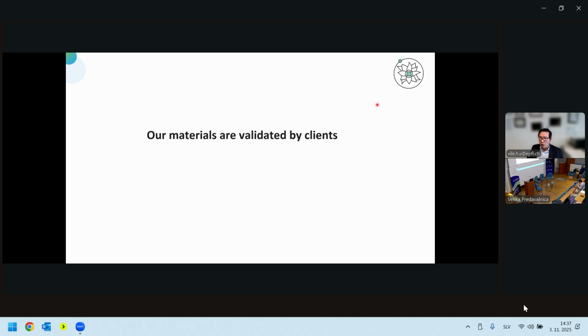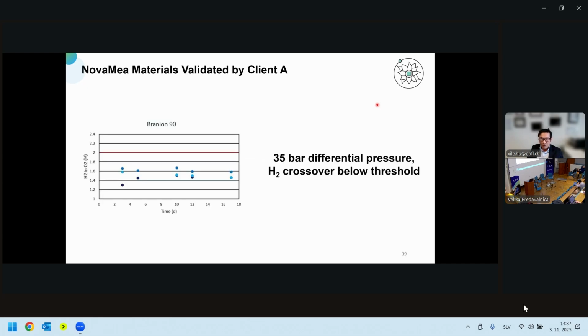So anyway, I'd also like to show you that our materials are not only validated by ourselves. I'll show you some client data. This is one client that has been doing differential pressure of 35 bar, so dry cathode at 35 bar, and they found our membrane has passed the hydrogen crossover test. This is a real test, and really important, because in real electrolysis you want to do dry cathode high pressure, because a lot of the energy in compression of hydrogen is wasted in the first 30 bar, in fact.